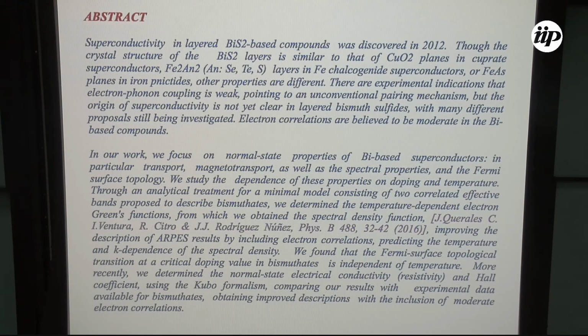Well, this was the abstract. Basically, the compounds were discovered in 2012. And the interesting thing, as I will show you in a moment, is that the crystal structure of these bismuth S2 layers is quite reminiscent of the layers in the cuprates, the copper-oxygen planes, or the planes with iron and different arsenides or chalcogenides in pnictide and chalcogenide iron-based superconductors. But there are other properties which are different.